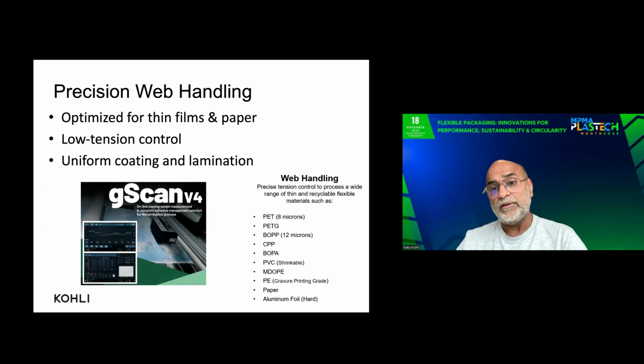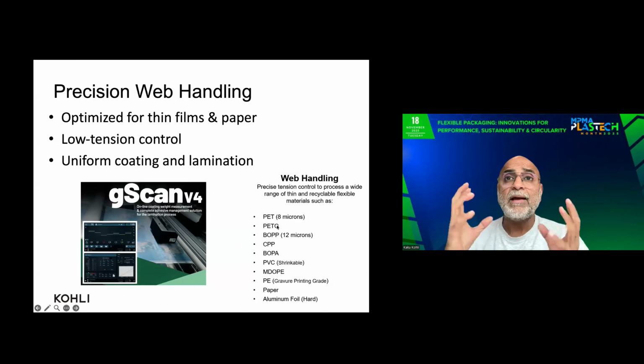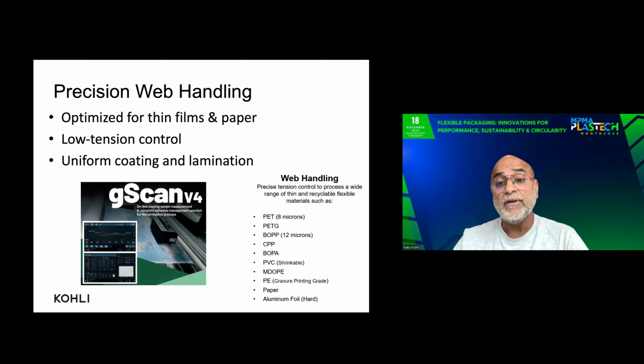So as you see on the right down here, today's machines can go as low as 8 microns in polyester, PETG used in shrink wrappers, BOPP as low as 12 micron. I think in India, we are reducing further to 10 micron very soon. CPP, BOPA, shrink PVC, MDOPE, polyethylene, paper, and aluminum foil.